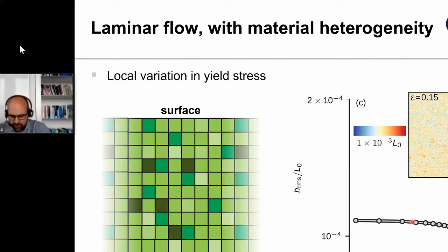Coming back to this question of what happens for laminar models, this is a continuum calculation that we have carried out, in which we assume a heterogeneous material in which the yield strength in subsurface volumes of the material, indicated by colors, differs randomly. And then we compress it. We get a random surface that's shown on the top right, but our scaling plot does not show self-affinity. So this is the picture of having different grains and different orientations that deform and give rise to surface roughness.